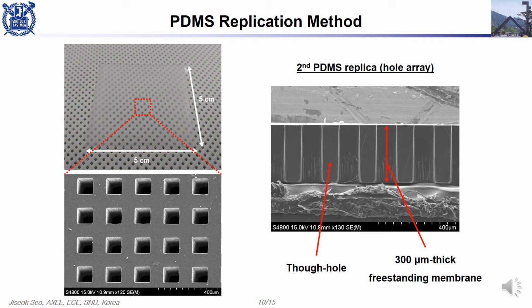The size of membrane is 5 by 5 cm in this image, and the size can be enlarged if 6 or 8 inch silicon mold were used. This membrane also shows the same structure with silicon mold. And at the right SEM image, you can check that 100 micrometer size through-hole arrays were successfully fabricated. The thickness of this membrane is same as the depth of hole arrays in the silicon mold.